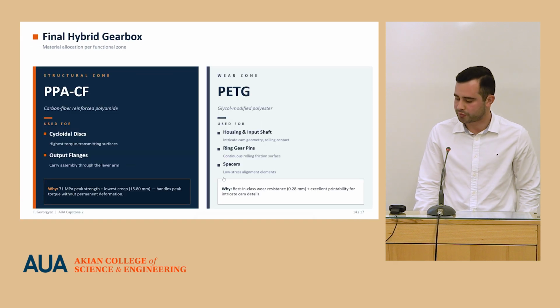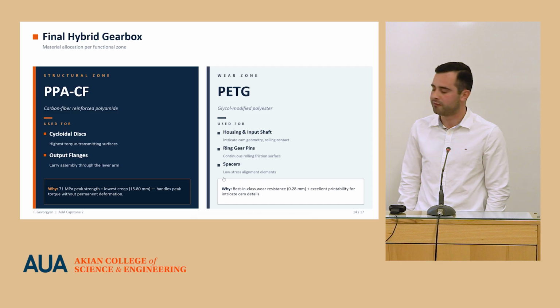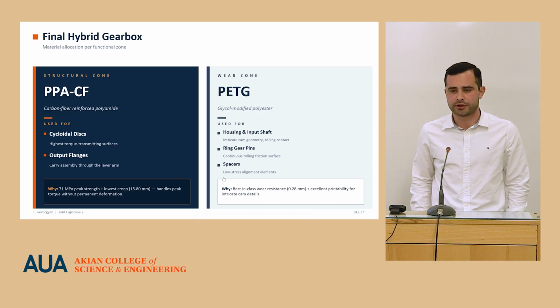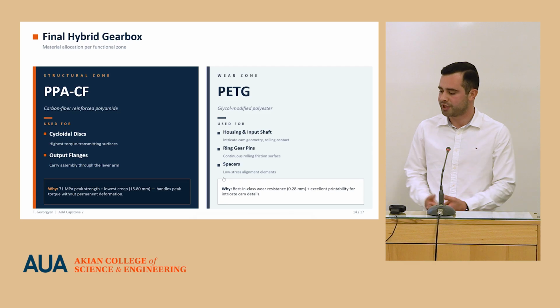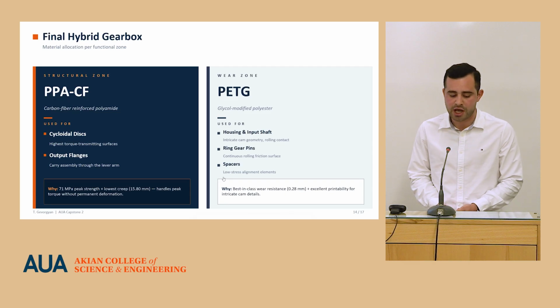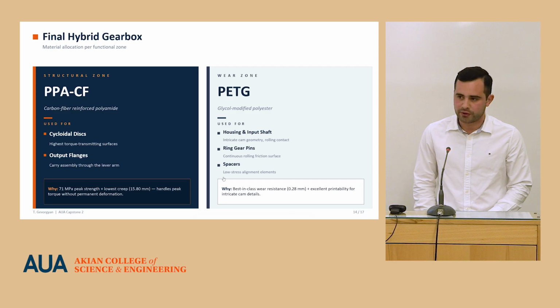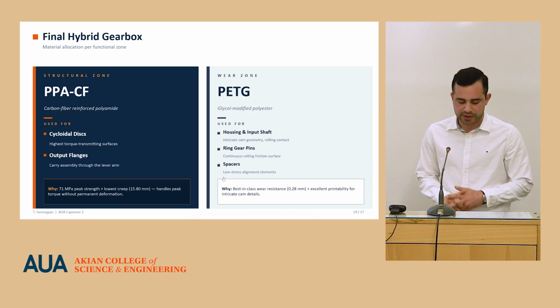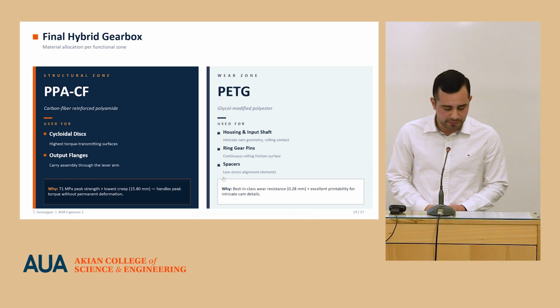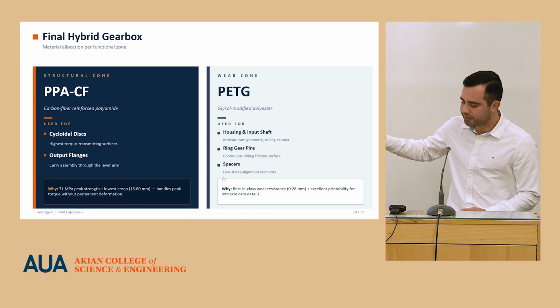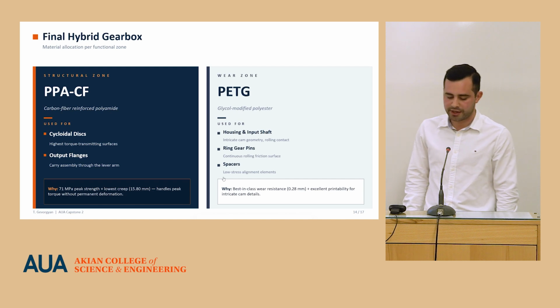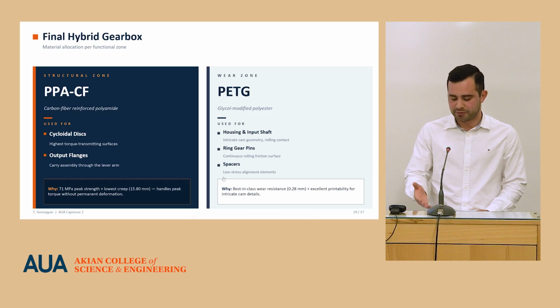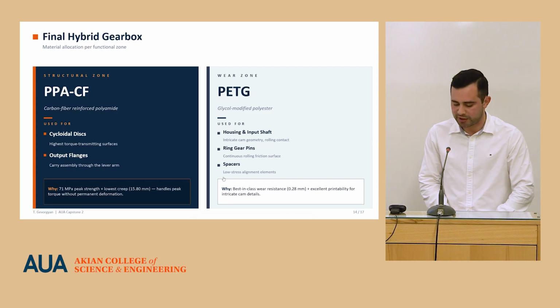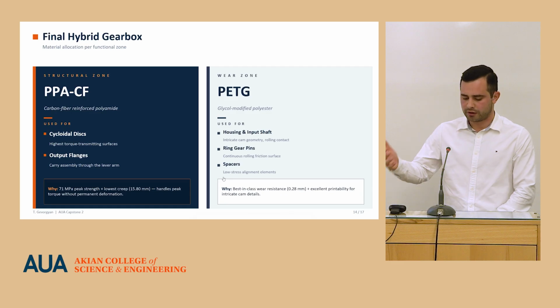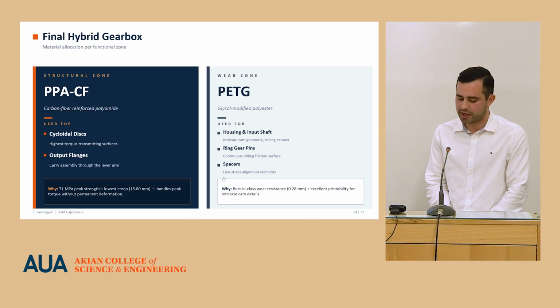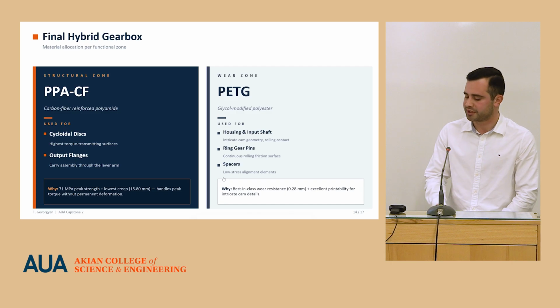Here is how I chose what material to use for each component. For structural zones, for the components that take the most pressure and most forces inside the cycloidal gearbox, I used carbon fiber because it holds up to 71 megapascal strength, and it had the lowest creep. I used it for the cycloidal disc and output flanges, and for the wear zones where the contact happens the most, I used PETG because it had only 0.28 millimeter loss in the diameter in the wear test. I used it for the housing, input shaft, ring gear pins, and spacers.